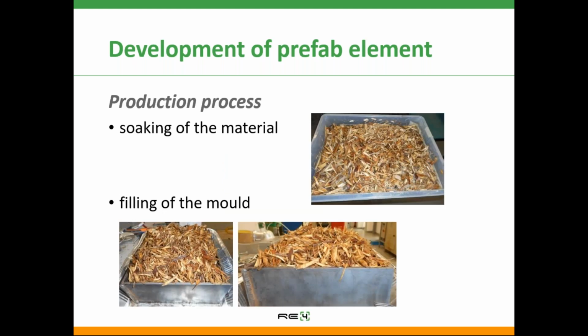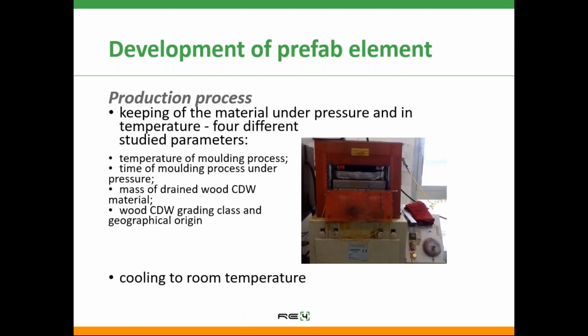Then the second step was the soaking of the material, reported in the picture in the upper part of this slide, and the selected material was soaked in water. Then there was the filling of the mold, as shown in the photos in the lower side of the slide. Soaked material was introduced in the mold after being roughly drained of the water. Depending on the quantity of material to be introduced, preliminary pressing steps were carried out in order to compact the material. Then the material in the mold was kept under pressure and at temperature in a hydraulic press.